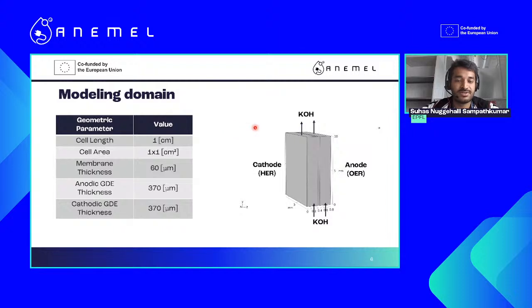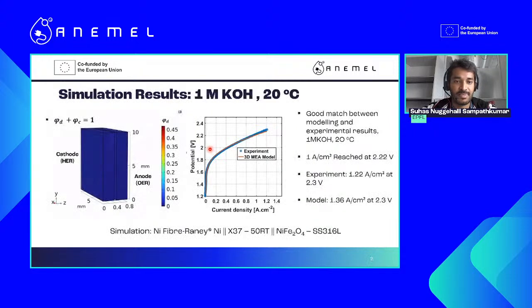Here is a representation of our modeling domain. We had a 1 cross 1 centimeter cell area with 370 microns of thickness, KOH flow rate from bottom to top, and then the anodic and the cathodic chambers with the assumption of a membrane thickness of 60 microns, which is pretty much the average membrane thickness in AEM electrolysis.